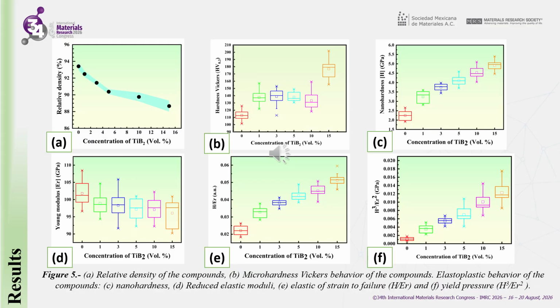As illustrated in Figure 5, the outcomes encompass the relative density of the samples, the behavior of the Vickers microhardness, and the analysis of variance of the elastoplastic property results for each sample in relation to the addition of reinforcing particles. It is evident from the relative density data that there is a decrease in this physical property as the concentration of reinforcing particles increases. In addition, the Vickers microhardness displays an inverse correlation with relative density. As the concentration of reinforcing particles increases, this mechanical property also increases, reaching a maximum value of approximately 180 Vickers hardness.